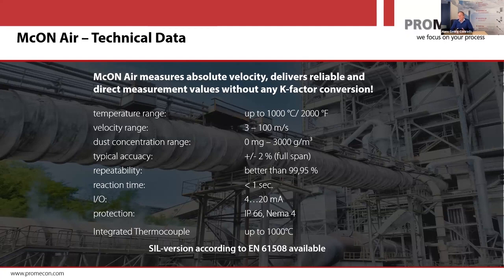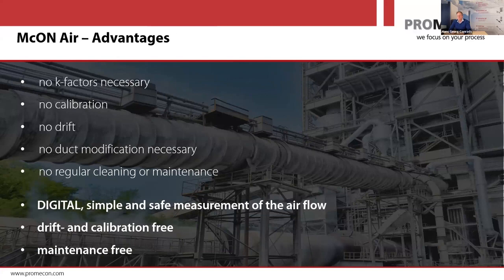And that's really what has been our recipe in the cement industry, to have such a high repeatability of our signals and such a low maintenance requirement. A reaction time of smaller than 1 second. And of course, integrated thermocouple if necessary in order to accomplish the temperature measurement. We also have an SIL version of this, but this is not so interesting for cement. Many power stations use that because of the safety aspect of boiler safety. So also power stations are using our system to optimize their combustion.